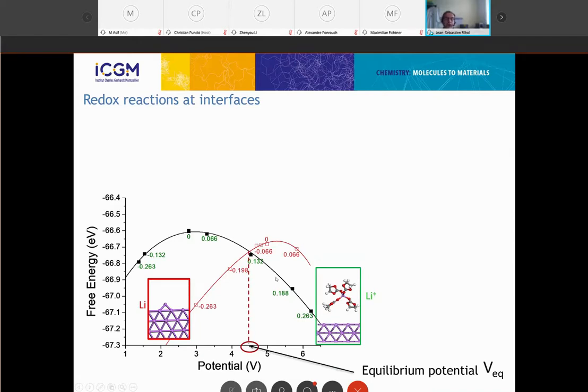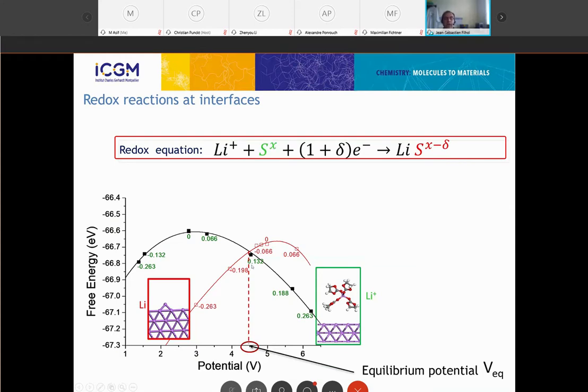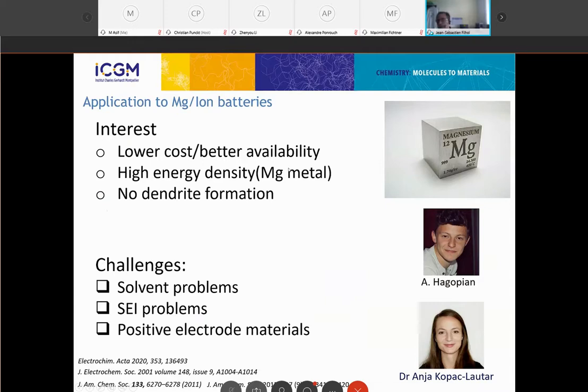When the two free energy curves just cross, we get the equilibrium potential associated with the redox system. We get the redox equation, and we can even get the number of exchanged electrons. In this case, that will be close to 1. Not exactly 1, because it's also including the surface polarization that is needed to maintain the potential constant. So below this potential, the reduced lithium metal will be the stable form, and above it will be lithium plus. So by using this formalism, we are able to investigate the electrochemical reaction on the surfaces or in the double layers. So now I will switch back to magnesium.